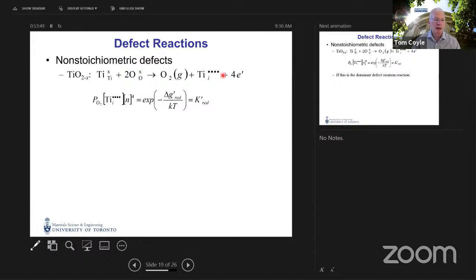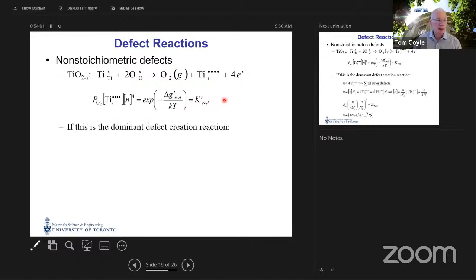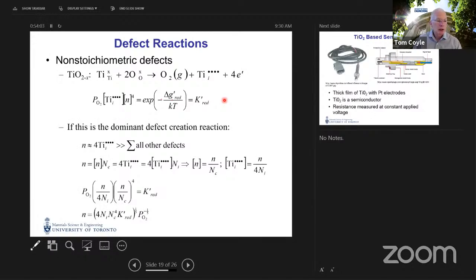Again, we can write down the mass action expression and then substitute for the number of titanium interstitials in terms of the number of free electrons. And again, ultimately derive an expression that relates the number of electrons in the conduction band to a constant, this time multiplied by the oxygen partial pressure to the minus 1/5.